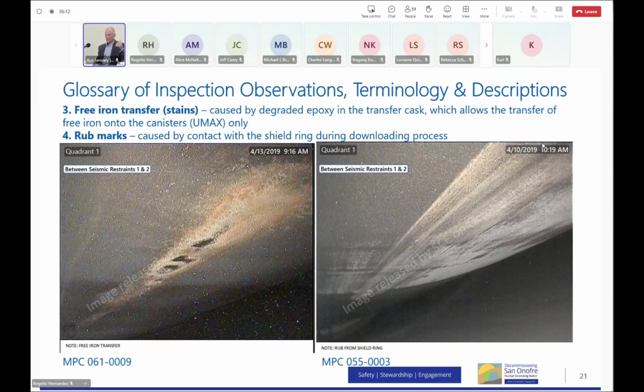Well, the cask has an epoxy coating on it. It's carbon steel, but it has an epoxy coating. Unfortunately, the cask that we were using, that we rented from Holtec, had a hole in the epoxy. So there was some carbon steel showing, okay? So that carbon steel rusted. So now it sits there for about 2 days. We have to weld the lid on, take the water out, vacuum dry it, then seal weld the ports. So it's about two days, maybe longer.